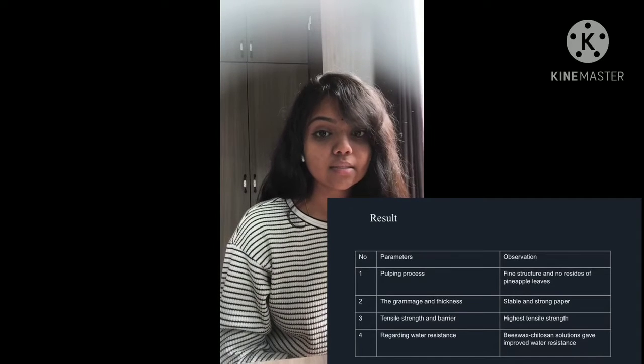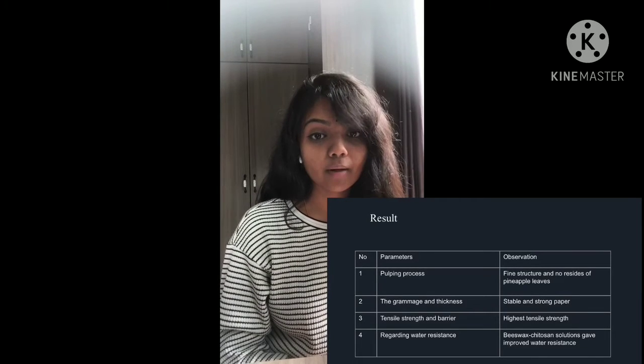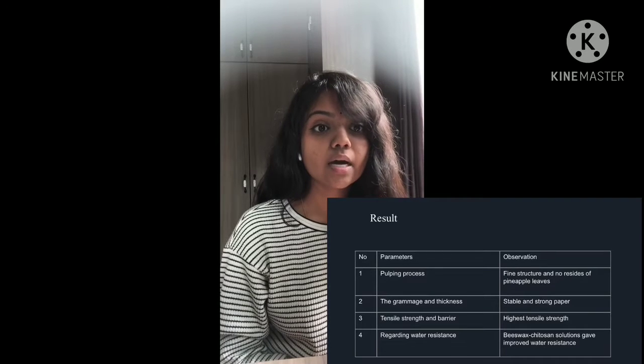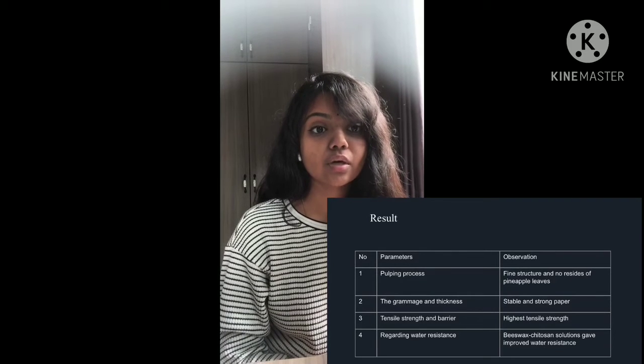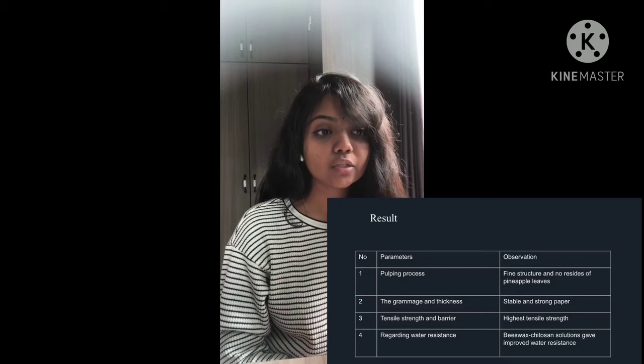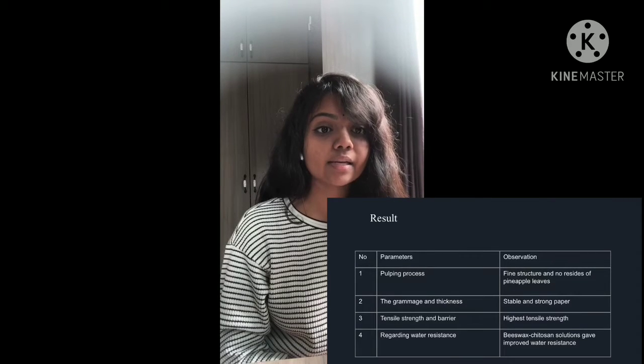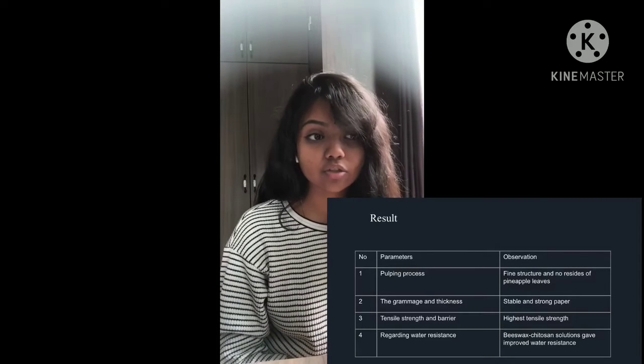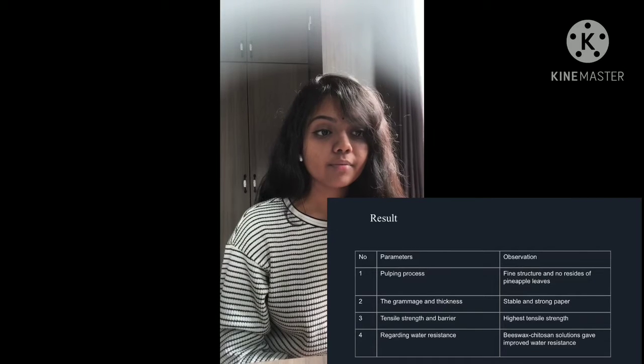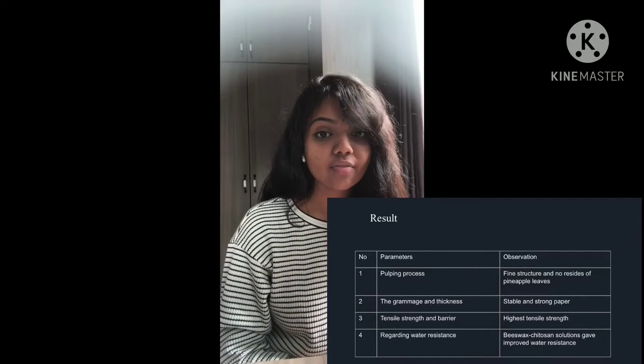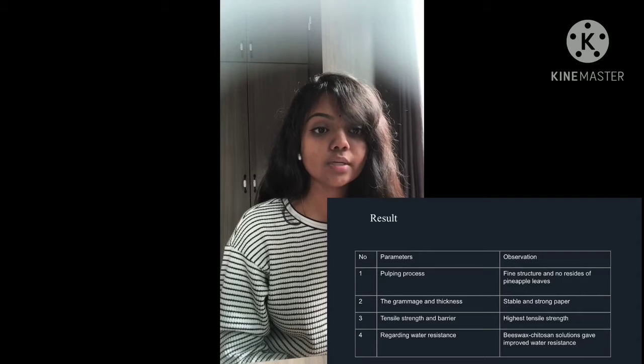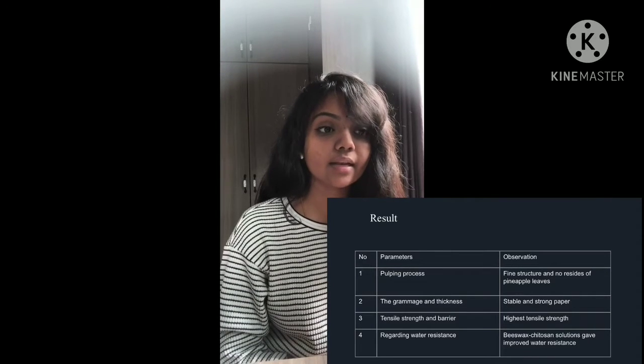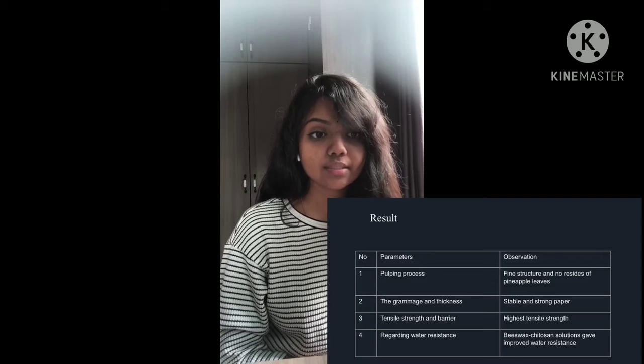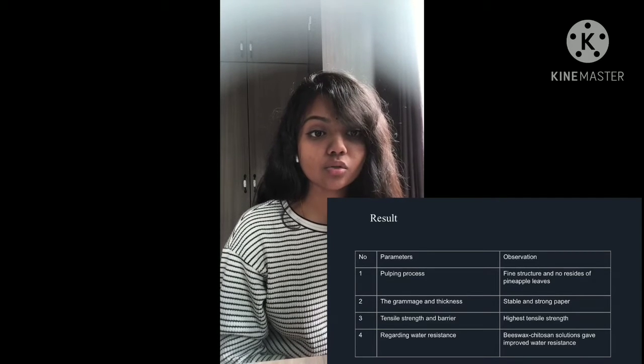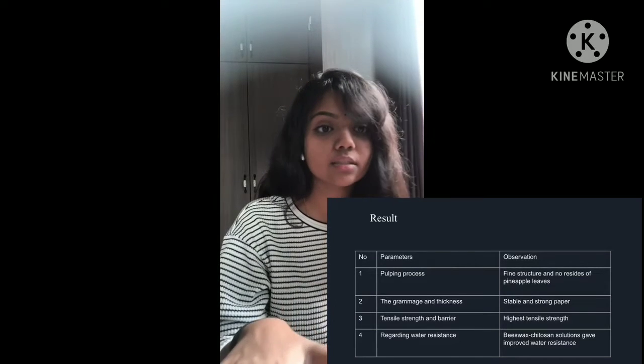So on the results, there were 4 parameters. The first parameter was the pulping process, and the observation was a fine structure and no residues of the pineapple leaves. Next was the grammage and the thickness, and the observation was that it was stable and strong. The third parameter was the tensile strength and barrier, and the observation was that it had the highest tensile strength. And lastly, regarding the water resistance, the beeswax chitosan solution gave an improved water resistance.